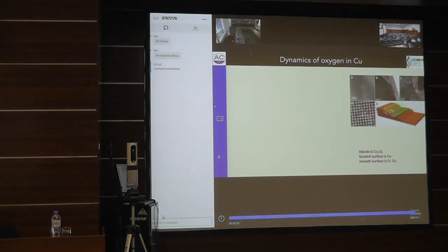Now, the question is, how do we know that there are three stages here, and how did we analyze which is which? This is done by an electron microscopic technique. We freeze in any one of these states, and then we put them in a machine which allows us to do sample preparation. So we cut out a little lamella of the material, put it in a TEM, rotate it by 90 degrees, and study the phase composition. And then we can do all kinds of different things.